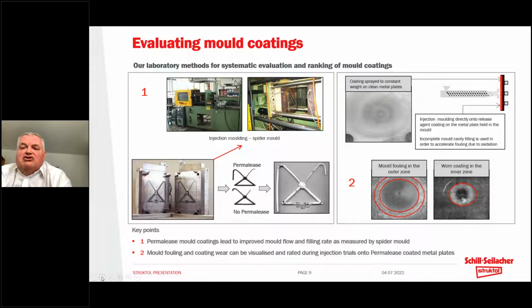We developed a rating system so we can really quantitatively rate the degree to which the mold is fouled. And this allows us then to give really an objective measurement to the degree of protection afforded by any particular mold coating. Going further then, the method on the right, method number 2, allows us to really directly visualize the performance of the coating applied to a mold surface.